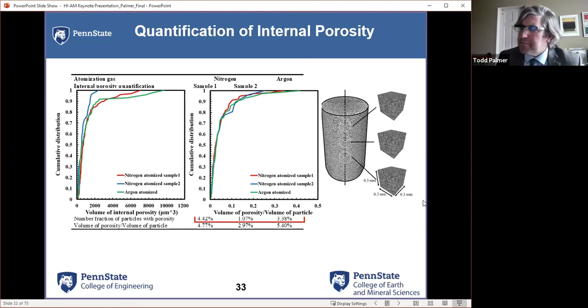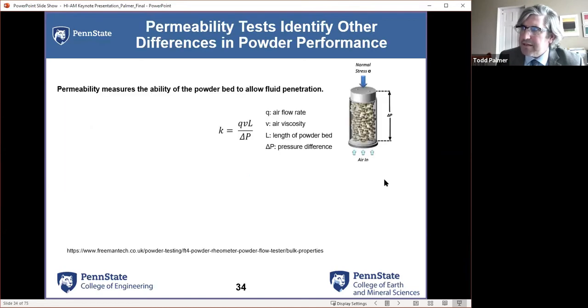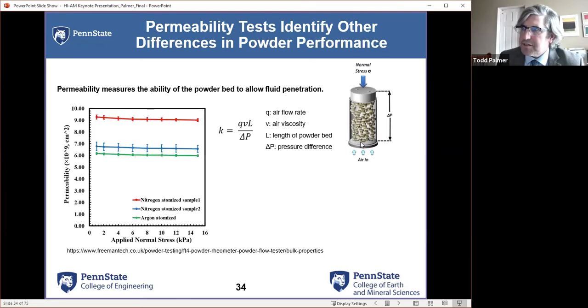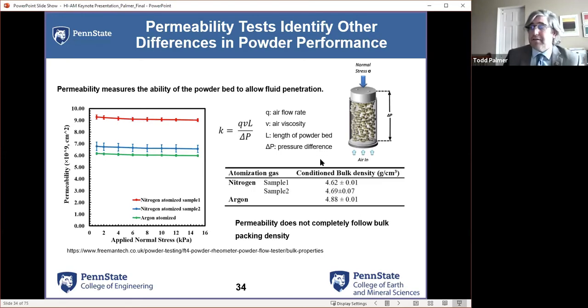The next thing to think about is I have a whole lot of powder in here. And one of our issues initially, and this is a better one to see it in, is that the void space is not just internal to the powders. It's also external to them, and it sits in how the particles pack. A way to measure that is through a permeability test, where you flow air through the powder with a normal stress on the surface. And what we tended to find was that there were differences in the permeability between the powders, and primarily one of the nitrogen atomized powders had a much higher permeability, which means it was really a difference. So they didn't follow the bulk packing density.